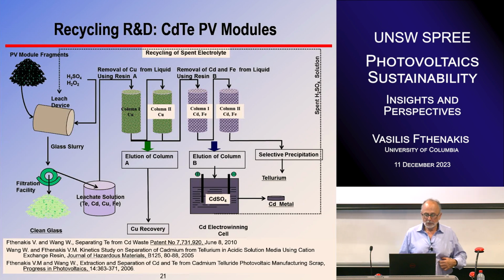Okay, so recycling technology, again, it is developed. You can see here a schematic of technology we developed at Brookhaven National Lab several years ago, starting with module fragments in the hydrometallurgical operation, using something inexpensive, dilute sulfuric acid, in this case only about 0.5 to 0.7 molar, and peroxide. Then we leach the metals and the semiconductor elements. We leave glass that we still need to make cleaner to get it back into float glass.